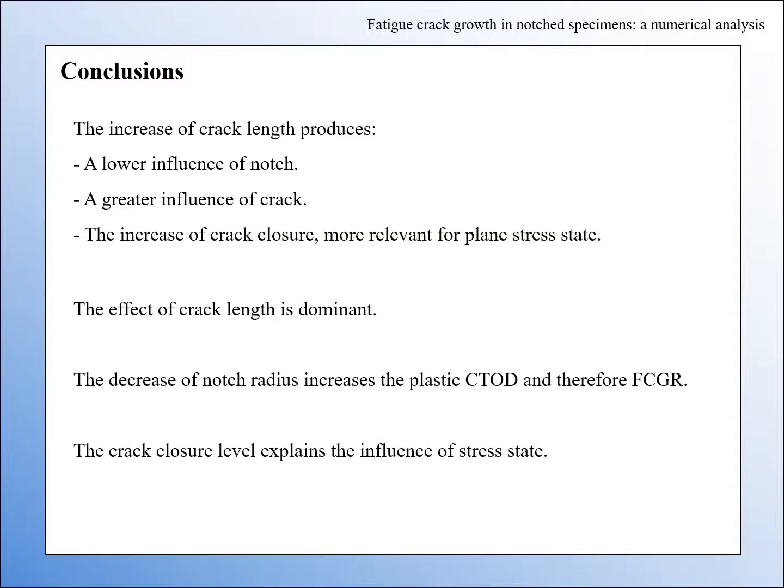The main conclusions are: the increase of crack length produces a lower influence of notch, a greater influence of crack, and the increase of crack closure, particularly for plane stress state. The effect of crack length is dominant.